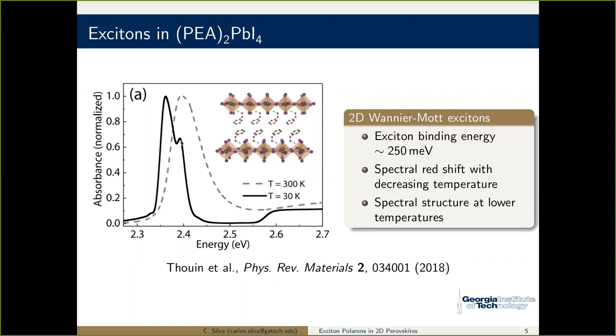But again, I can show data that rules out that as at least the main argument. That's a k-based effect that takes a lot of k for this to show up. And if I do a thickness dependence of the single layer perovskite, with 2 layers, 3 layers, 4 layers, this doesn't change, and that's not consistent with the Rashba effect. People talk about vibronic progressions. There is no phonon or combination of phonons that would account for that. And I will show you, I think very convincingly, that these are distinct excitons. They're not a progression of the same exciton. So it's not a vibronic effect.